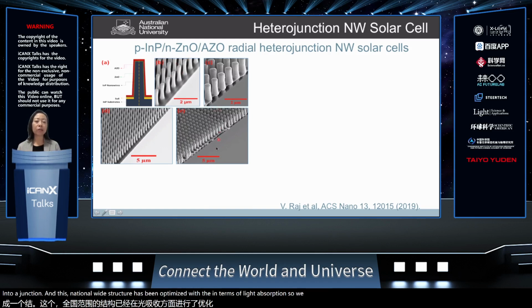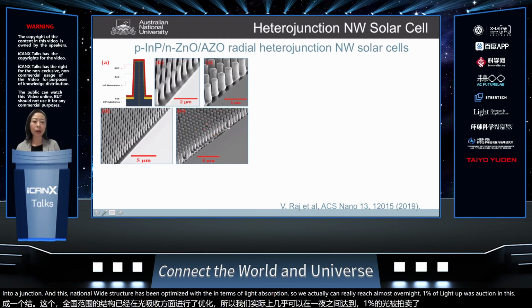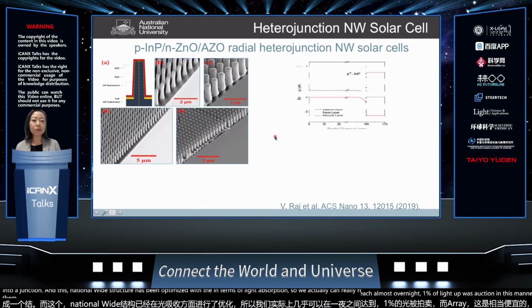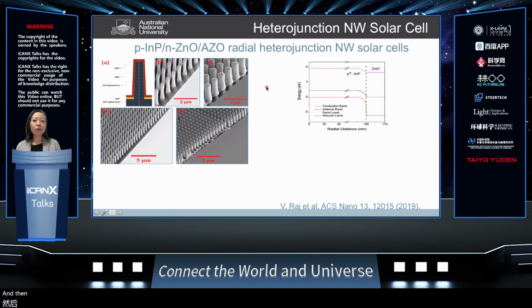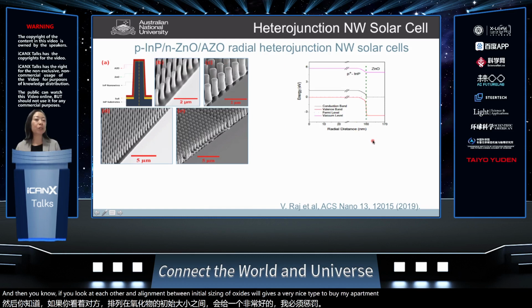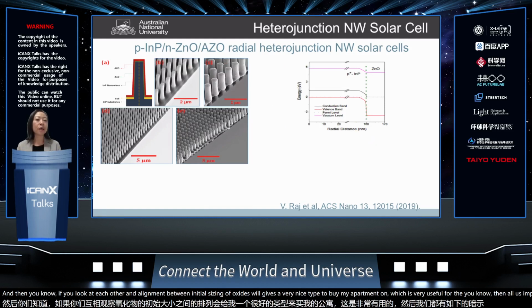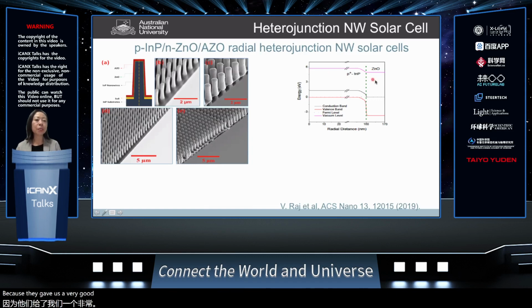So we actually can reach almost over 90% of light absorption in this nanowire array with quite, you can see, small volume of material. And then, if you look at the band alignment between indium phosphide and zinc oxide, you get a very nice type 2 band alignment, which is very useful for solar cell application, because it gives you very good electron transport, and then it blocks the majority hole diffusion in this case.